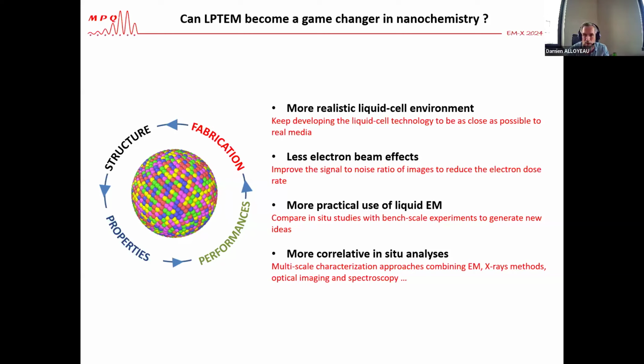So with many other colleagues and experts in liquid cell TEM, we discussed how we could induce this change of paradigm. And we realized that we need to have more realistic liquid cell environments, meaning that we have to keep developing liquid cell technology to be as close as possible to real media. We need to reduce the electron beam effect, and for that we need to improve the signal to noise ratio of our images. We need to have a more practical use of liquid cell EM, which implies that we always have to compare in situ experiments with bench scale synthesis. This is the best way to generate new ideas and design materials in different ways.